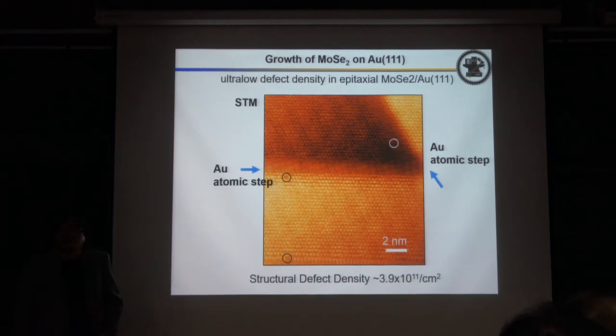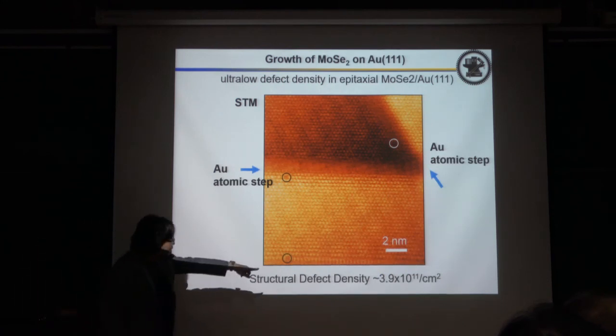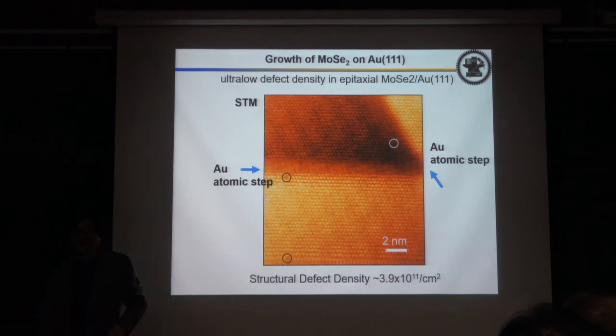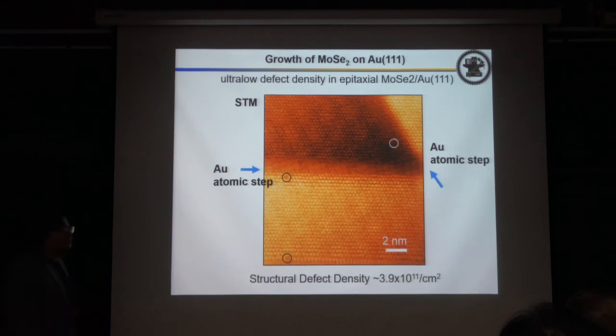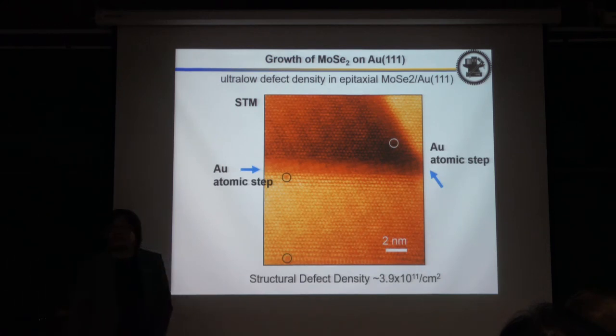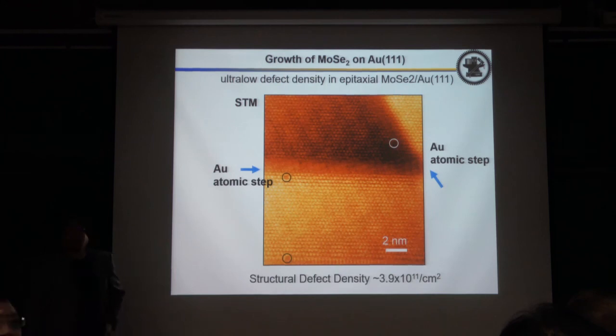Oh, this is good. The milestone is 10 to the 12, so we already achieved it. It's far less than silicon. Silicon is 10 to the 6, but that is 3D. This is surface defect density per centimeter squared. I think for silicon it is 10 to the 6. And why can 2D tolerate this? Yes, gallium arsenide is also very low. So why can 2D tolerate it?